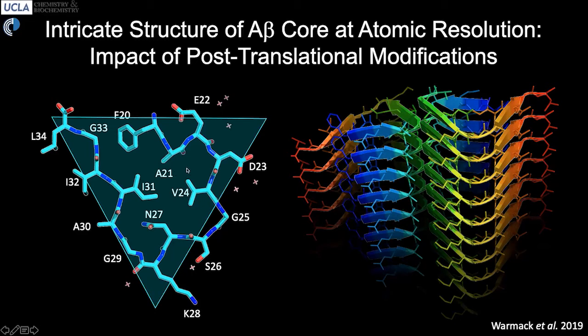This was determined by electron diffraction also here at UCLA to atomic resolution, so they could see exactly where every atom in this core was. And this is sort of an unusual conformation for a peptide forming this type of polymer. It was this triangular structure, which would have, again, been very, very difficult to characterize otherwise.